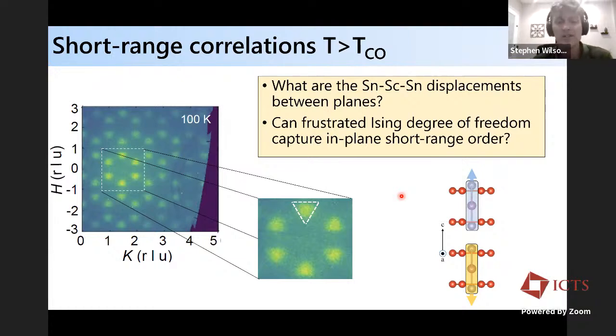And so one thing we'd want to do is quantitatively show that this is what's going on. What we wanted to understand, in this high temperature regime, is whether it's true that we have these trimer units displacing up and down, and whether the in-plane correlations are really driven by this frustrated Ising degree of freedom. So can we capture the triangular shape of the diffuse scattering?